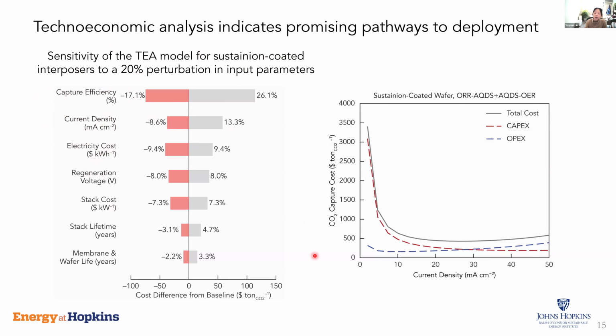So we achieved on the order of 50 milliamp per square centimeter current density. But one can argue that this is still not the industrial current density that one would expect for an electrolyzer, which is on the order of hundreds of milliamp per square centimeter. But we want to make the argument that for DAC, because of the low CO2 concentration in the air, we don't necessarily need to go to extremely high current as long as we're being cost competitive.